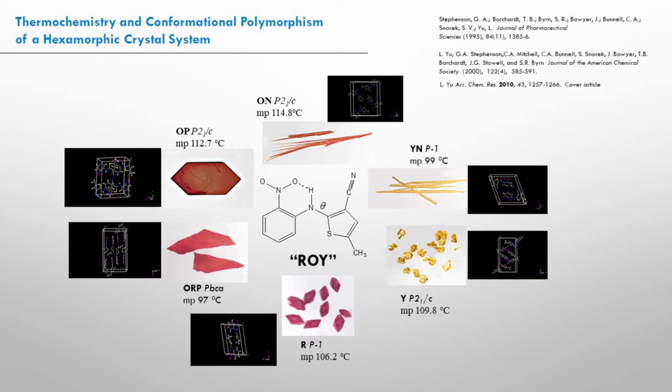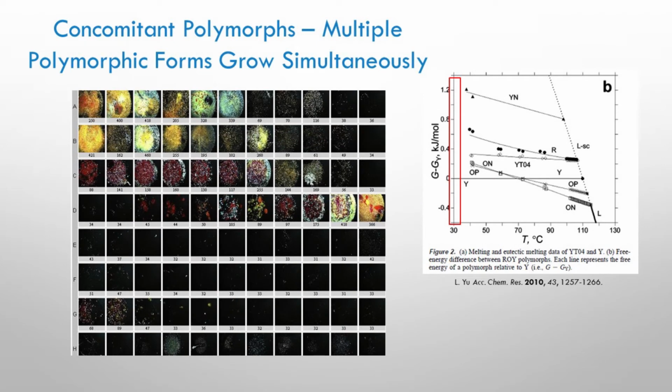But you look at the melting point differences, they're significant among these different forms. So this is a classic case of polymorphism, and it led to some very good science by one of my fine colleagues, with our group, and then with one of my colleagues. I had done some high throughput screening from the early 2000s, just showed where multiple crystals would crystallize simultaneously from the same exact crystallization, and there was little control over what form would come out. You'd get mixtures of forms.